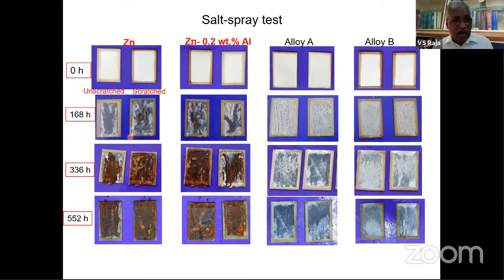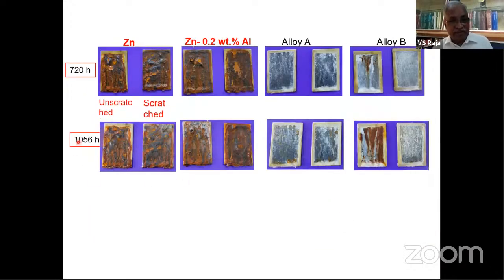Look at this, 168 hours, rusting here. Now at 552, no rusting taking place. Look at the kind of increase. Not only 552, you can look at this, it has reached almost 1056 hours, and you don't see much increase in the corrosion of these coatings. So you can simply tweak it by adding a small element.